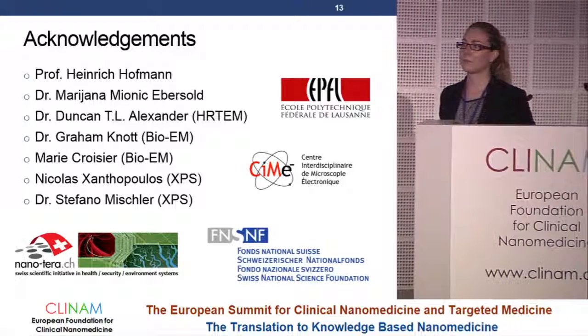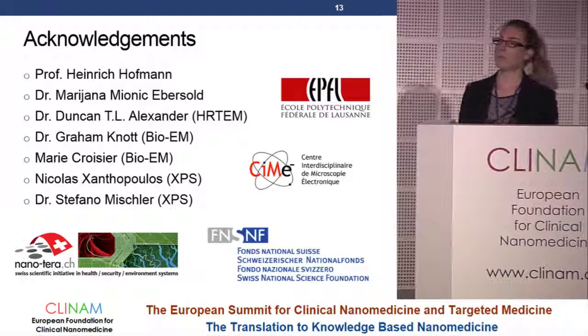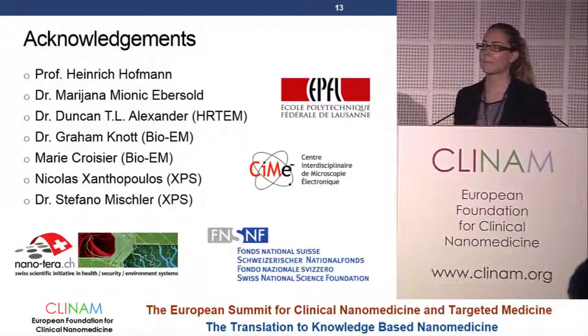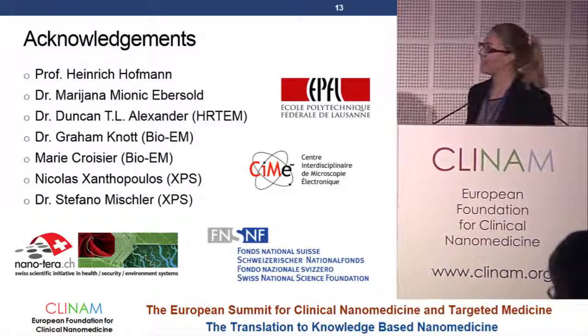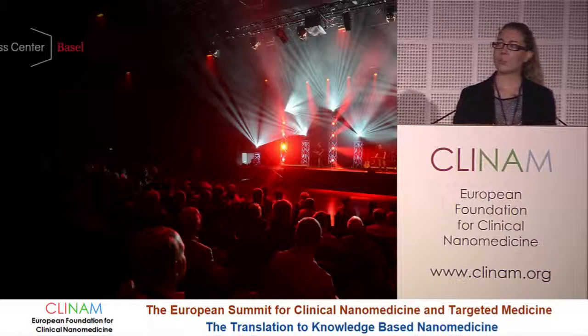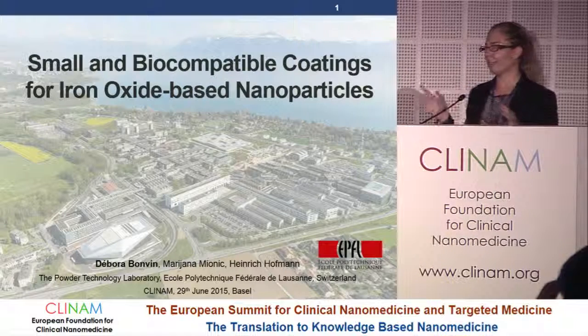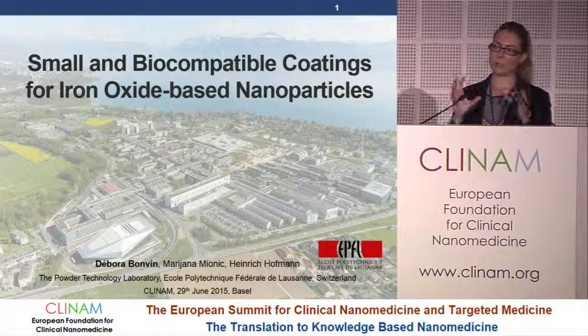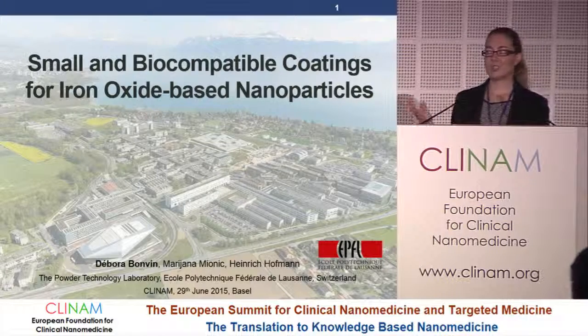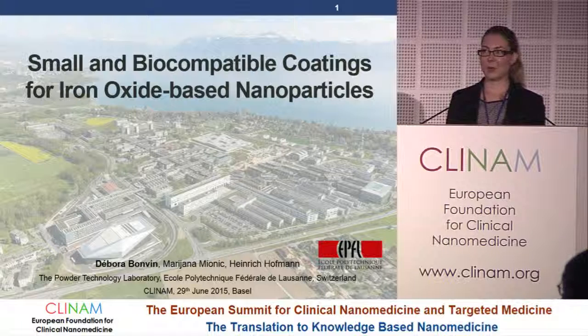Question from audience: If I understood correctly, you had a large increase in particle size when you put folic acid on the surface — from around 20 nanometers to roughly 80 nanometers. Can you explain why this increase was observed? The speaker responds: What I showed is the hydrodynamic size, which is not the crystallite size but accounts for the water molecules around the particles. Additionally, it is possible that you are measuring two to three particles together, as the coating may be bridging nanoparticles together, contributing to the increased size.